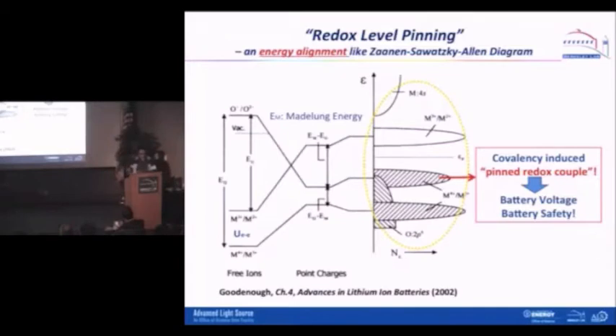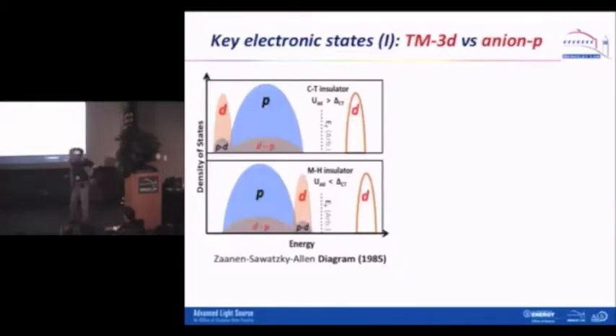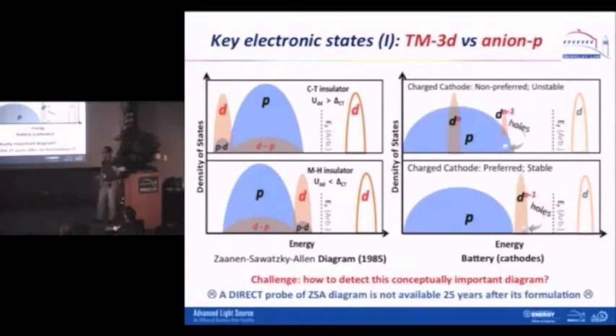Why is this redox level or energy alignment diagram very important? This is associated with the so-called Zaanen-Sawatzky-Allen diagram in fundamental physics. Whether the d level sits above or below your p level determines two different kinds of insulators. If I translate this diagram into a battery cathode, you always have a redox pinning on top of this d state. You always have a little bit there, from the covalency between the p and the d. However, it is determined by whether this d state is way below or above it. It determines whether the majority character close to the energy level is majority p or majority d.